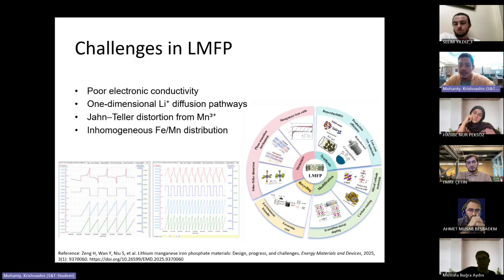So we could discuss this further. Maybe I'm not giving the most clear example of Jahn-Teller distortion, but because of this elongation of the ion itself, a structural strain or stress is generated, which degrades the lattice structure and does not allow ions to move freely. Again, Jahn-Teller distortion could be advantageous for ion transportation, because the stress and strain creates new pathways for lithium ion diffusion as well.